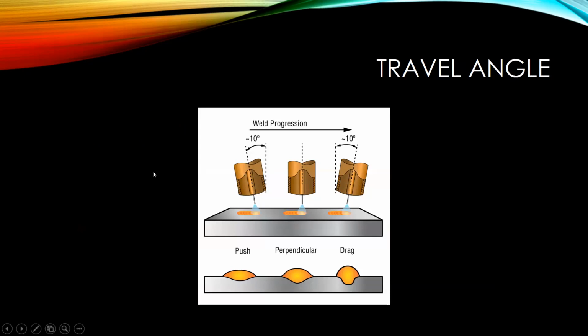So travel angle. Typically what I'll see a lot is using a push technique when you're using silicon bronze, especially when you're welding with pulse, you want to be on the leading edge of that puddle. So typically if you're moving from left to right, you'd want to be using this push angle.